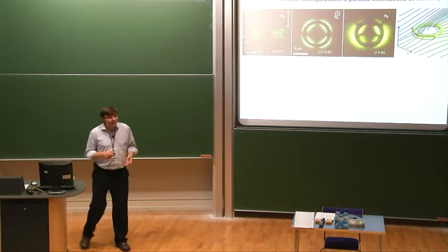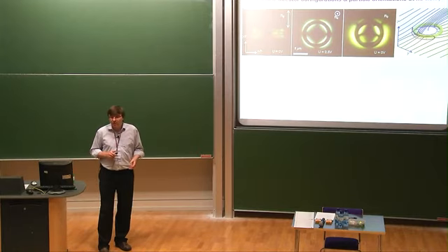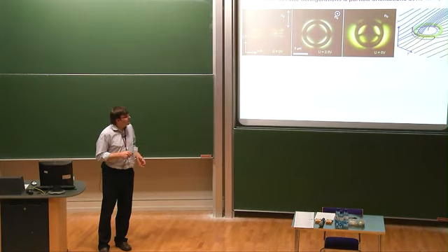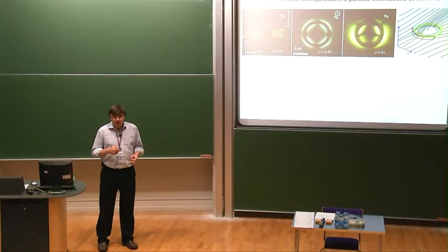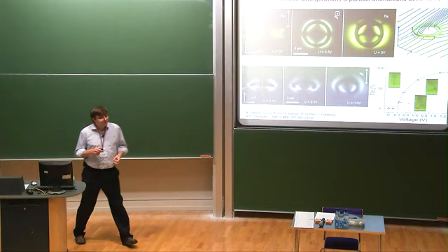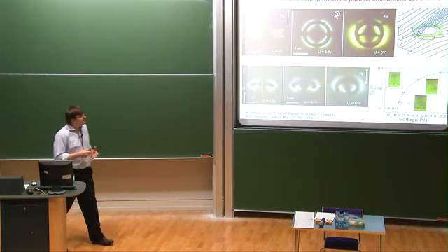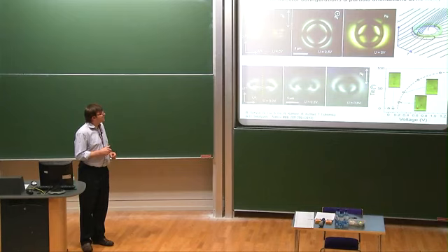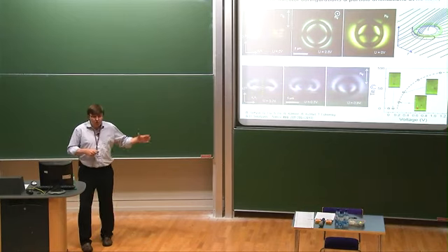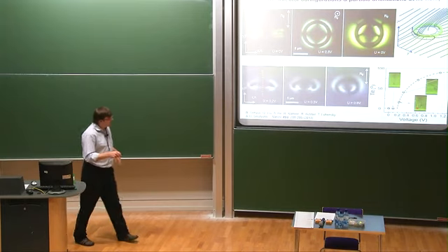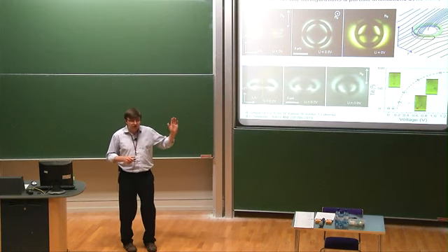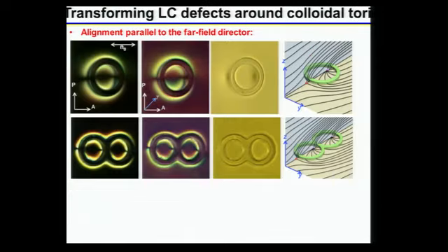Now, as we do it, obviously the structure of defects changes a lot, right? So now the defects you observe in here are different types of loops and point defects than what we saw before. Although they are topologically similar, the details of the structure of the director field are different, right? And so moreover, we can, as I already mentioned, continuously rotate those particles, right, as we apply voltage, and we can see from those cross-sections the particles will tilt, and we can do a lot of different types of structural transformations, but topology remains constrained, right?